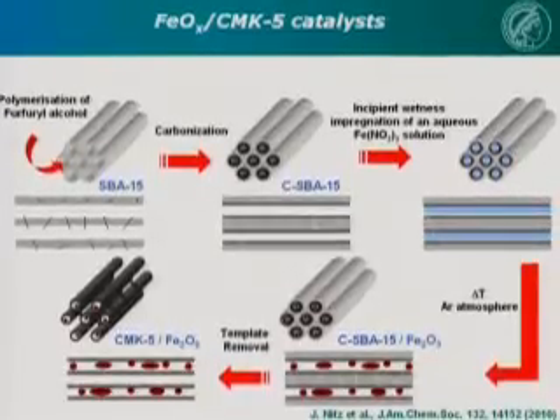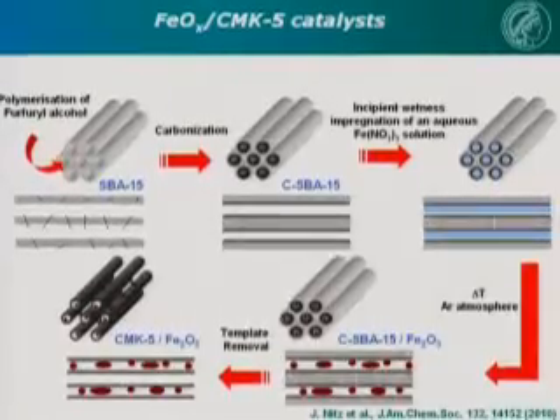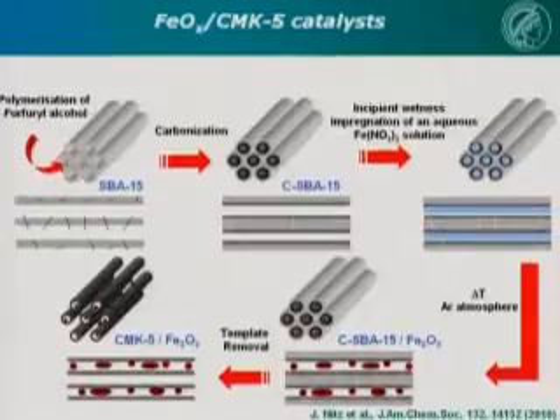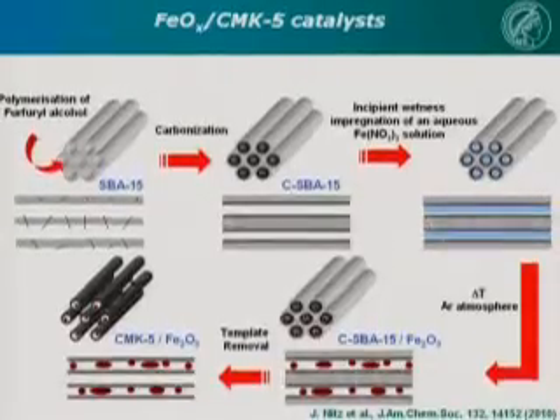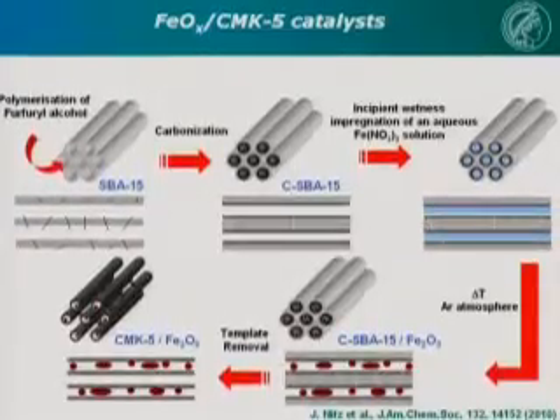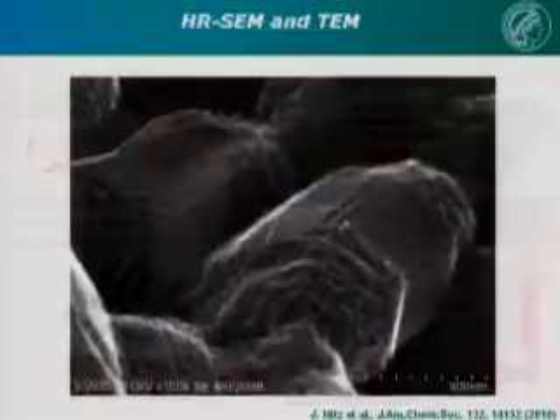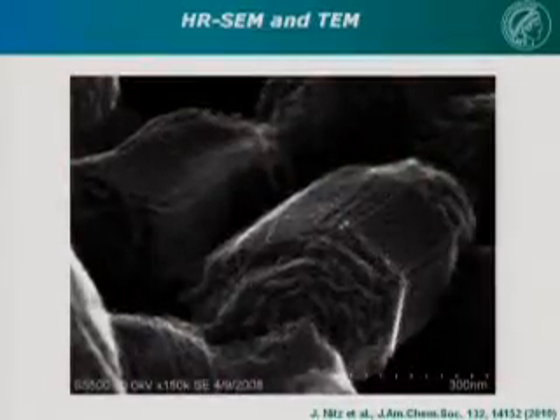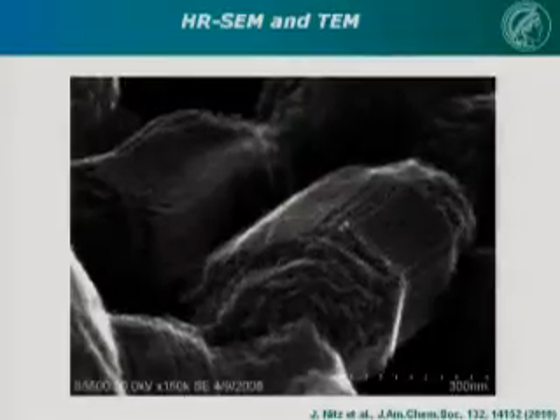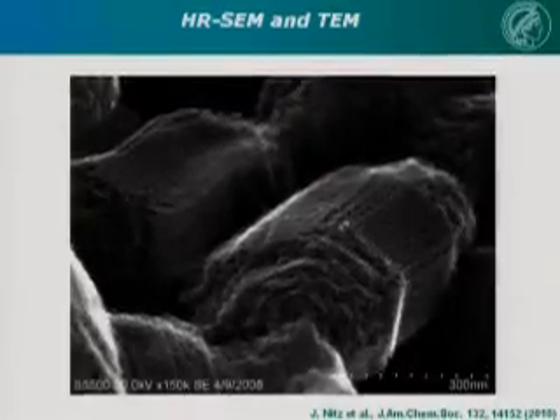formed from tubes, hexagonally ordered, and only in the inside of the tubes, precisely located in these 4 nanometer holes, we have iron oxide particles, which can then not grow any further. That's basically a size limit which we have imposed on it. I hope you can see that reasonably well. This is the material, what it looks like. It looks like a woolen sock, actually, a knitted woolen sock.